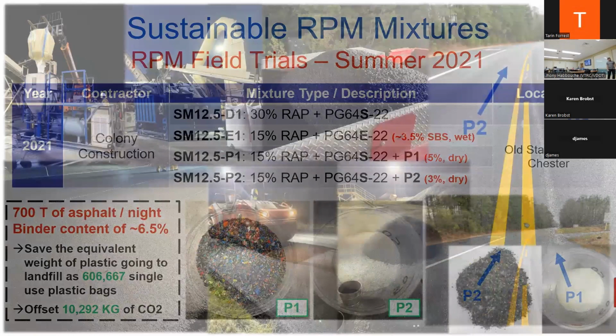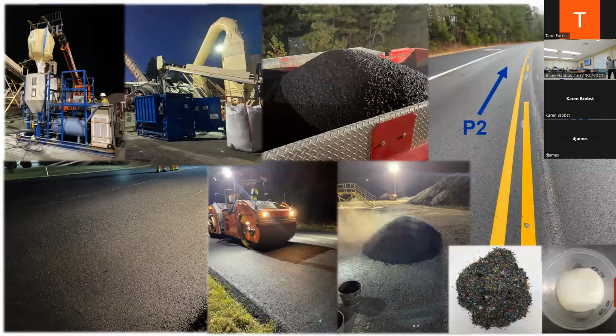So looking at some of the pictures, these are the fiber machines that we use to blow in the plastic. You see that small bag in the top left corner picture that gives the plastic, and that gets blown into the asphalt mixture. And then that's the asphalt mixture in the truck. It looks like regular asphalt, unless I tell you it has plastic in it. And that's being paved, that's during the paving operation.